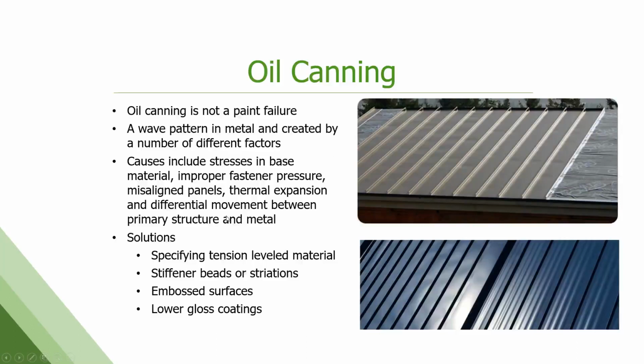Oil canning is a shape issue that occurs. Almost all light gauge steel, especially, is prone to this. It's one of the downsides of it. Basically, it looks like an oil can. It waves. You get buckles in the panels during installation. The causes include stresses in the base material, so if that base underlayment's not done right, you can get this effect. Improper fastener pressure, so if you're over drilling and pulling the panel too tight in one direction, or forcing panels together because they're misaligned, you'll get this buckling or oil canning.